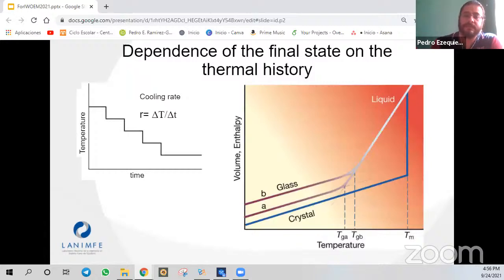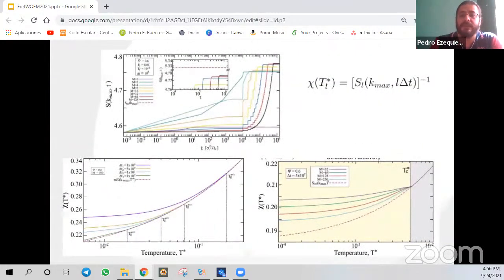As a first approximation to the dependence on the preparation protocol, we made a stepwise preparation protocol in which between each temperature change, we solve the NE-SCGLE equations. The cooling rate in the model is defined by the total number of steps and the duration of each step. What we found in this case is that when the cooling process is made above some critical temperature Tc, the system always finds the equilibrium state, no matter the cooling rate. In contrast, when the system is cooled down below Tc, a strong deviation from the supercooled liquid properties is found, and actually the system gets arrested in a stationary state, which depends on the cooling rate.